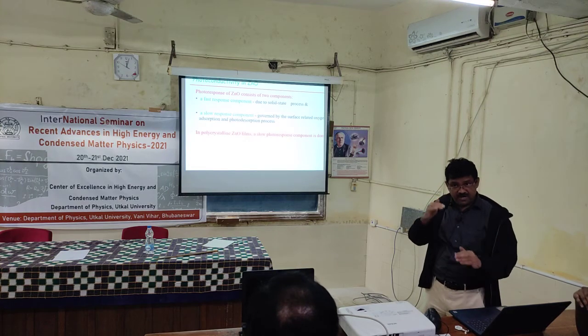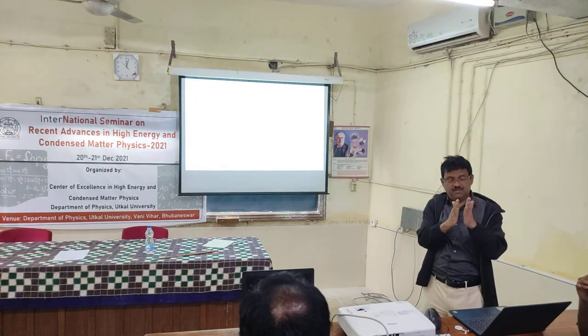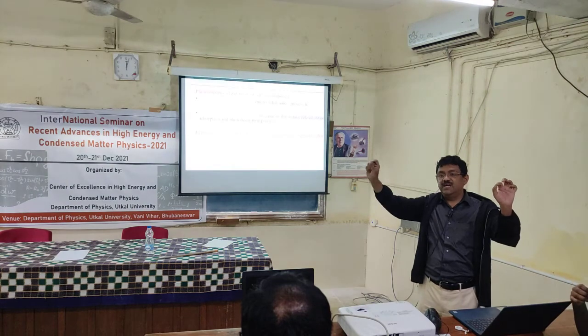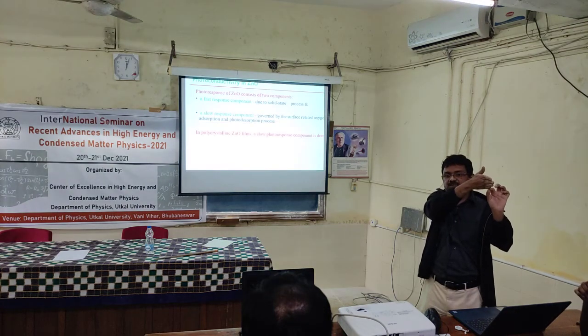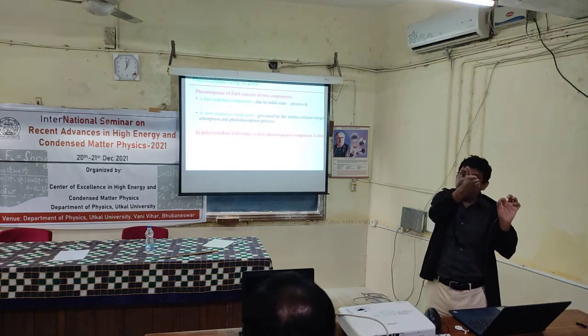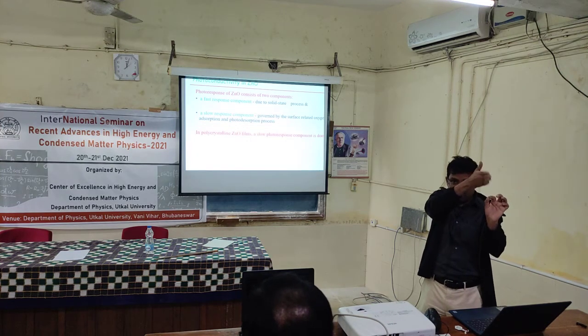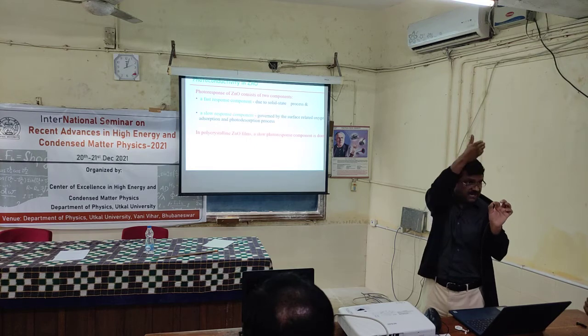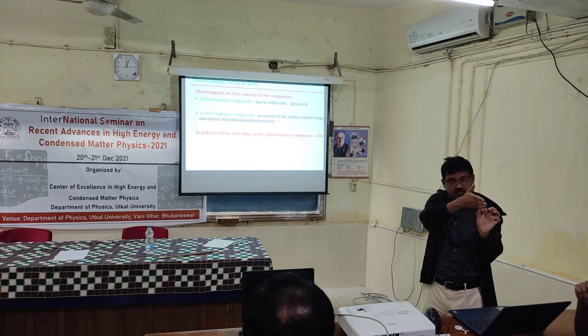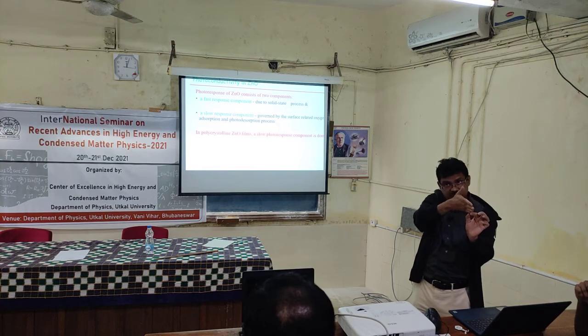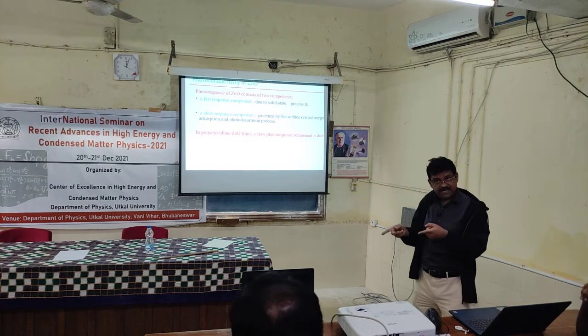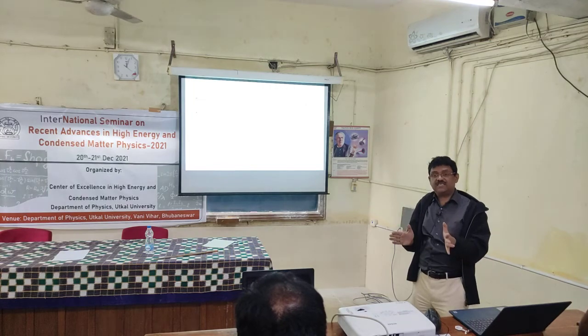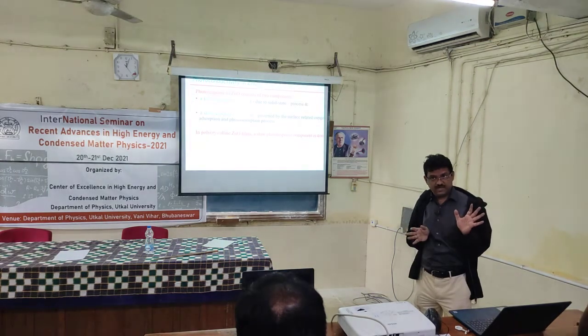If you look at the band gap of zinc oxide, the visible range wavelength is 380 nanometer to 750 nanometer, and zinc oxide is around 390. Beyond 380, it will be UV. So the band gap of zinc oxide lies very close to that border. That's why it is one of the best suited materials for UV detection. But the disadvantage, as I mentioned, is that they will recombine. Room temperature is not enough to dissociate them.